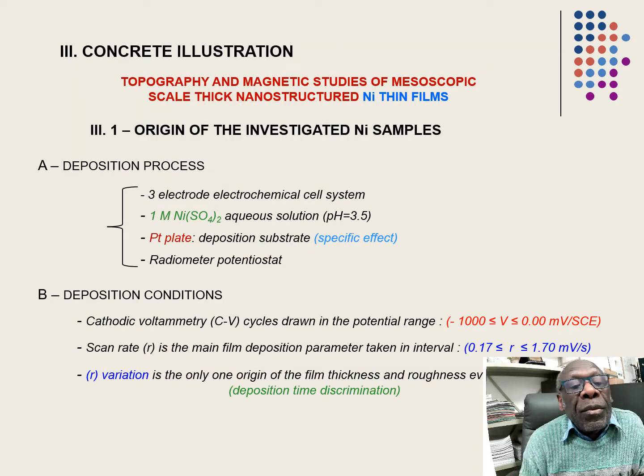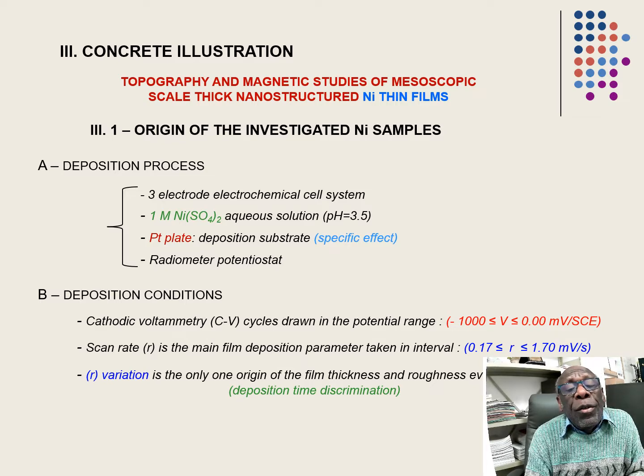Let's go to a concrete analysis, concrete result. I told that I use nickel thin films. Nickel thin films are here prepared by electrochemical process, for which the films are obtained by using the cathodic voltammetry cycles, for which the main variable is the scan rate of the cycle. The values of the limits selected are here presented, and from them the discrimination of the samples are then obtained by deposition time options.